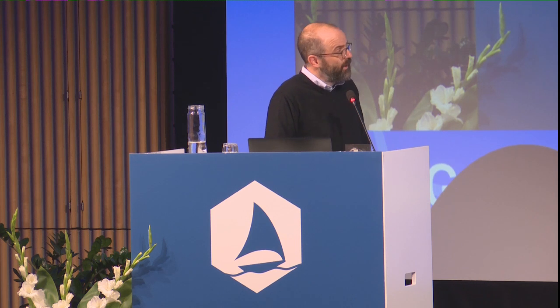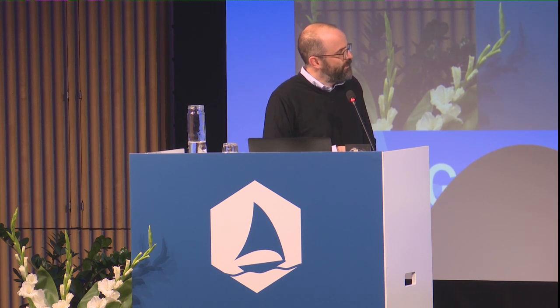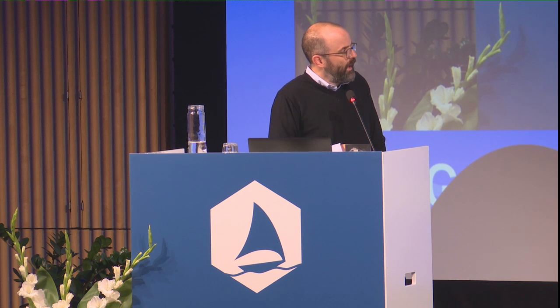What I really want to do is plot the gap in the system and how that evolves with pressure. Remember, in this scenario, this is not graphene aligned to two BNs, it's graphene aligned just to one BN layer. So we start off with a gap in the system that's about 30 meV. It's not quite perfect alignment, it looks like. And as we apply pressure, something interesting happens. First of all, the activation energy at the satellite point doesn't show any sort of variation. But the gap value that we extract at the charge neutrality point shows a diverging trend with pressure. So at 2.5 gigapascal, we've increased this gap again by nearly a factor of two.